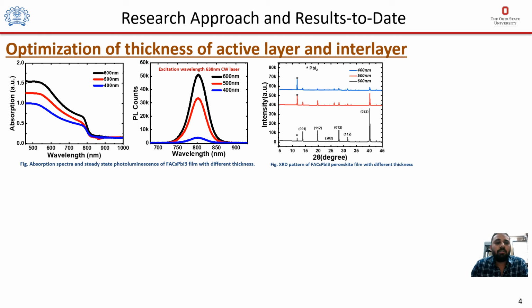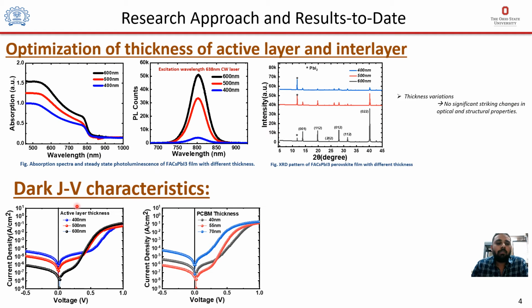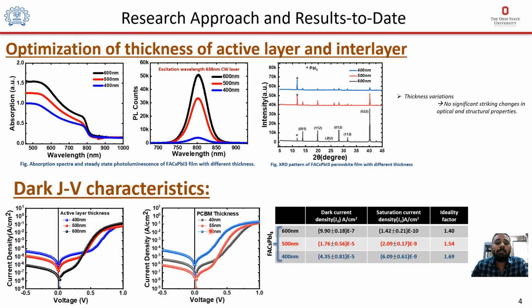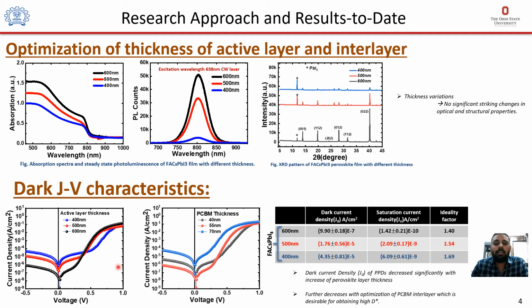Next, we have carried out some optical and structural measurements of the films of different thicknesses, and it has been observed that there is no significant change in the optical and structural properties. Next, we have fabricated devices of different active layer and interlayer thickness and deduced these parameters from the semi-log dark JV curves. It has been observed that with increase in the thickness, the dark current density decreases significantly, and it further decreases with the optimization of the PCBM interlayer.